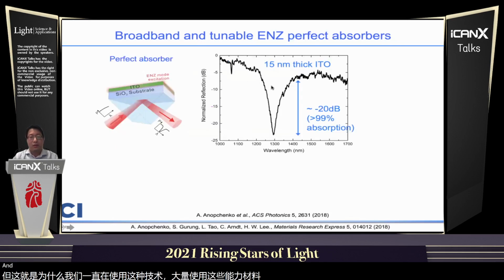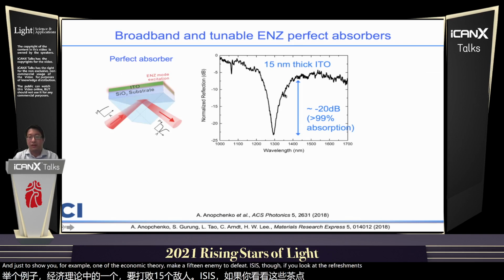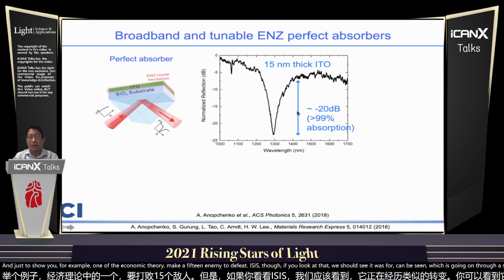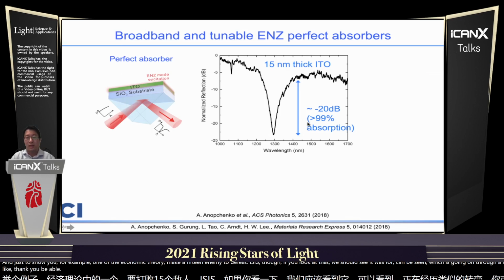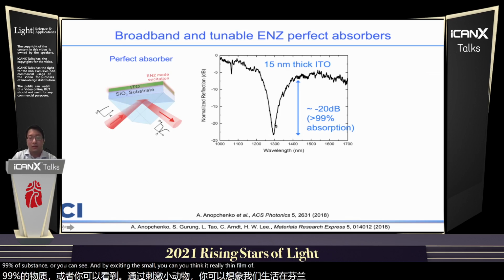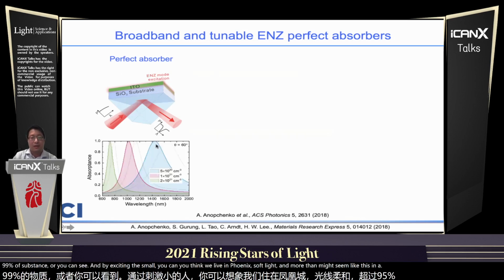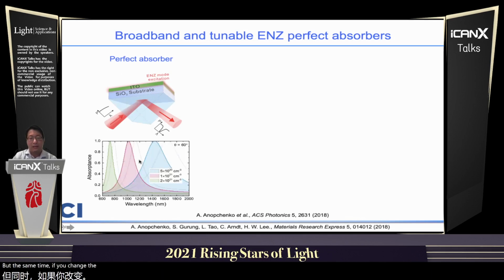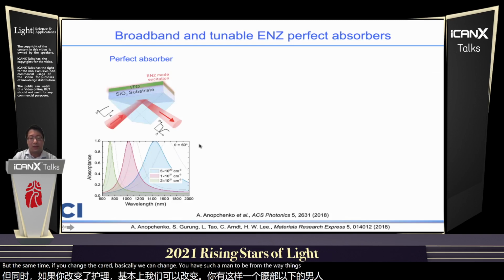And just to show you, for example, one of the materials we make, a 15 nanometer thick ITO. If you look at the reflectance, you see a reflectance dip here, which corresponds to an ENZ mode excitation. And you can see the amplitude is quite high, like 20 dB, which is close to 99% absorption. So you can see by exciting this mode, using a really thin film you can absorb more than 99% of light here. At the same time, if you change the carrier density, you can change the absorption band to a different wavelength as you decide.